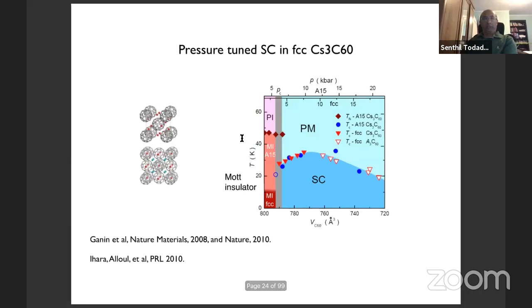Okay, now there's another entertaining example. This is in buckyballs, C60. You make a compound like cesium-3 C60. It forms an FCC structure, and at ambient pressure, this again turns out to be a Mott insulator, and it's a frustrated Mott insulator. It has a Curie-Weiss temperature of more than about 35 Kelvin or so, but it doesn't order down to very, very low temperatures. Now, if you apply pressure to this, again, there's a Mott transition, and you get a reasonably high temperature superconductor. It's like 30-something Kelvin Tc, right?